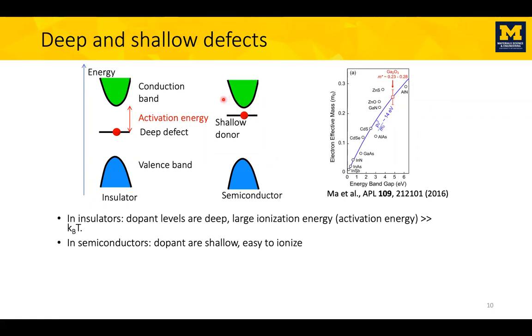That's what we want. In contrast, if you do the same process in an insulator, you will find that sure, you introduce the dopants, but the energy you need to pay to activate them is much, much higher, on the order of eVs. So at room temperature, those dopants do not become ionized, so that does not give you conduction. And so the dopants being deep means that this activation energy is typically much, much larger than kBT. Whereas in semiconductors, those are shallow and easy to ionize.